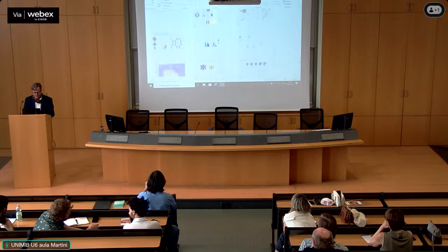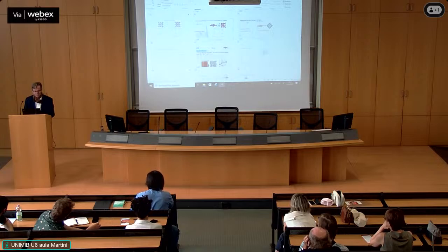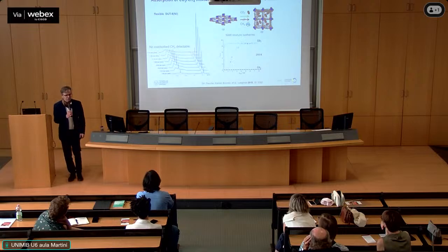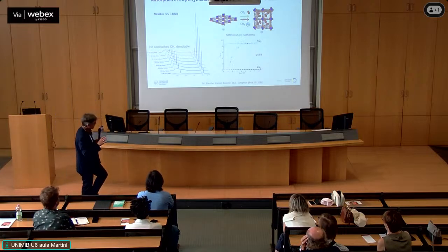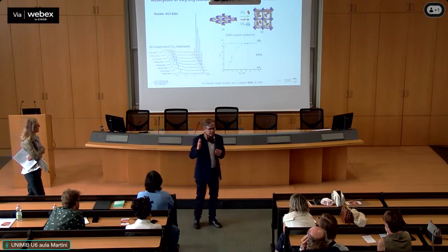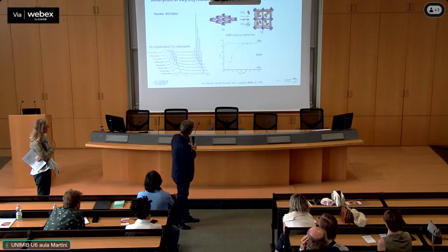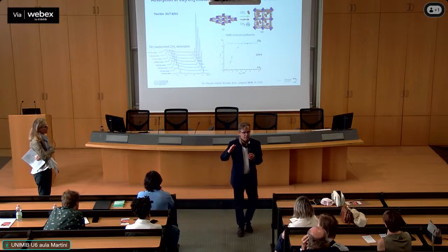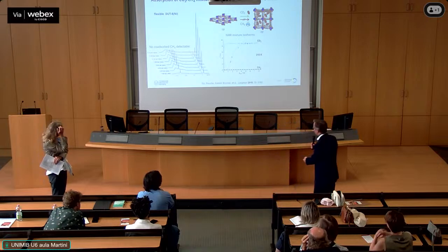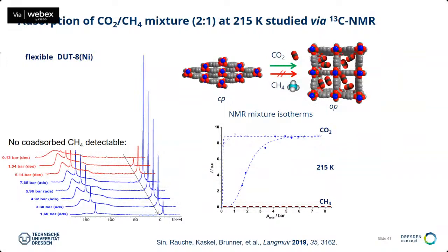Yeah, so this is a bit of a complicated question. In the example that I demonstrated, we have both gases in the gas phase, but only one gas is adsorbing in this case. So that's maybe a different situation here. But here it's not so much the ring current that is affecting the chemical shift, but more the limited degree of rotation. The CO2 is very much aligning inside the pore, and therefore in the static NMR experiment, it develops this tensor here. So this is a very broad tensorial signal, while the signal in the gas phase is very narrow.